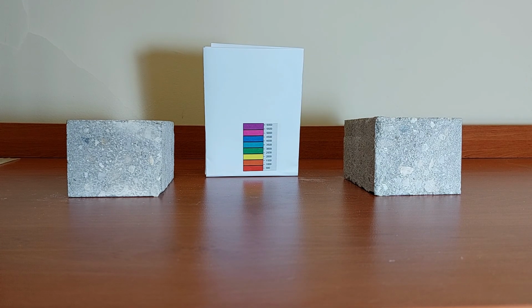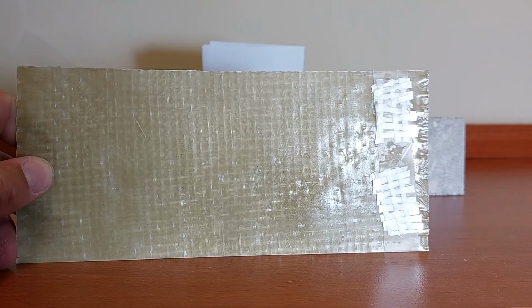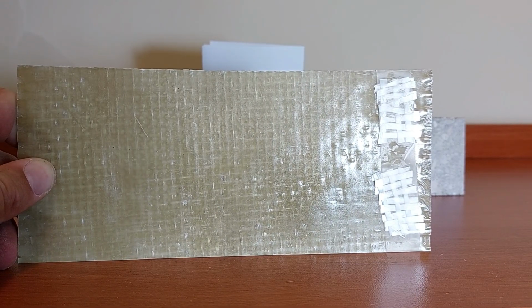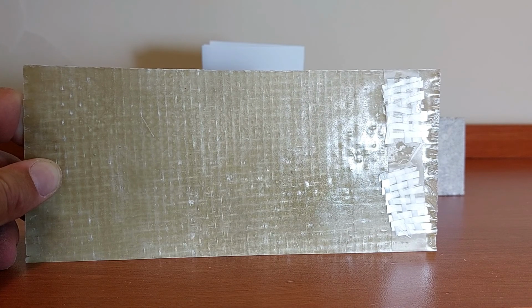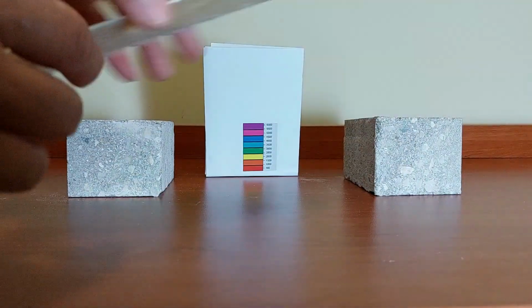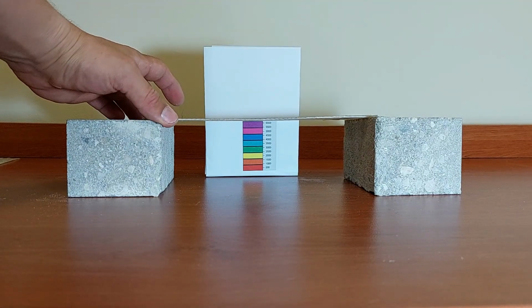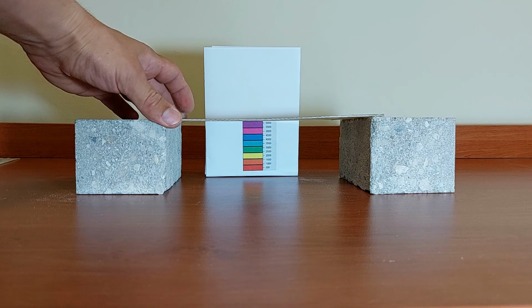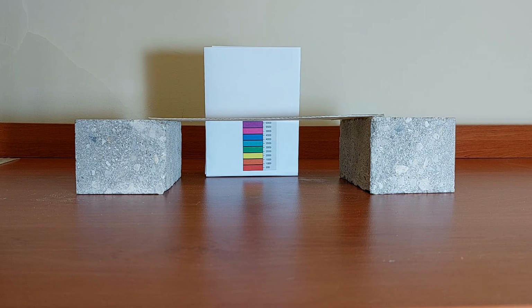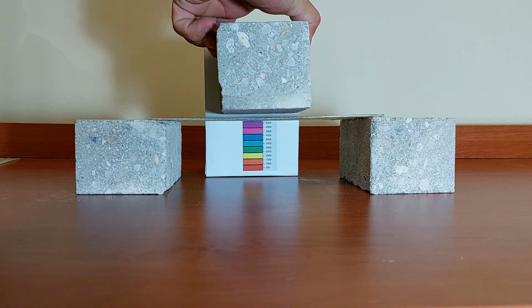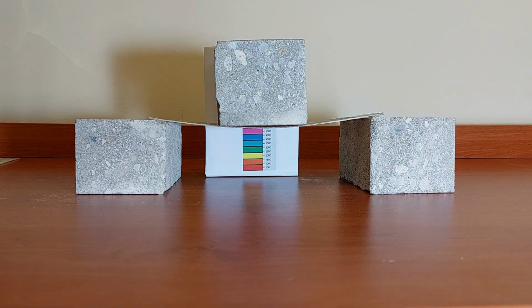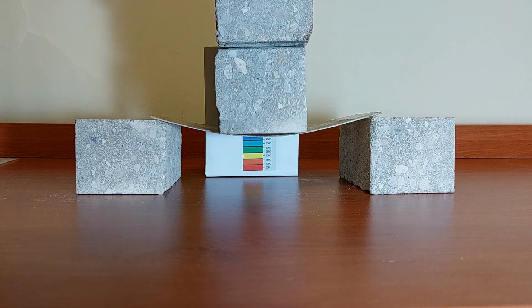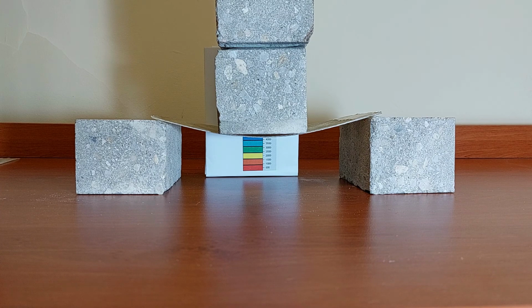And we're going to start with the first sample, which is woven roving laminated with vinylester resin, and we have two layers of this. I will put it here close to the scale, and now I will just add weight to see how much it will bend. So this is with around 1 kilo, and it's only one color down, and trying to add 1 kilo more, we have almost dark blue.